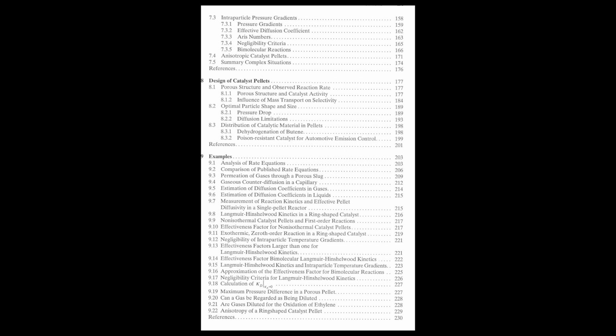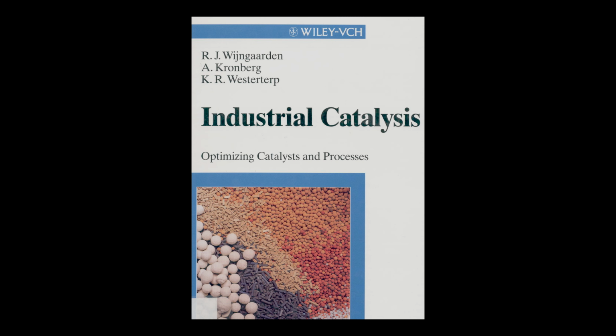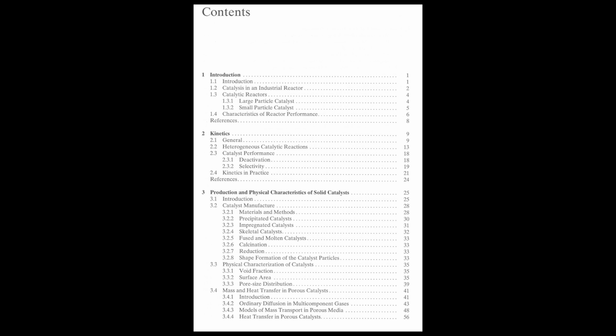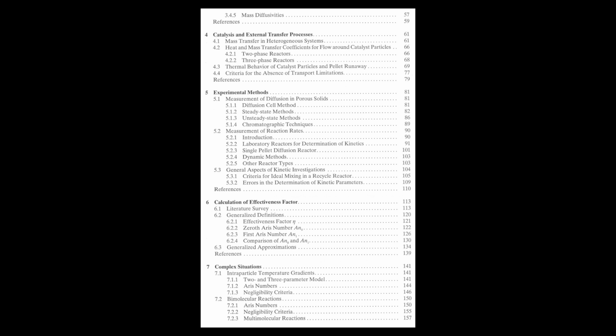This section gives us some practical guidelines and rules of thumb. It discusses criteria, with the Weisz-Prater criterion being a famous example, that can be used to estimate whether internal transport limitations, diffusion inside the pores, or external transport limitations, transfer from fluid to surface, are significantly affecting the overall observed reaction rate. How do they work? Basically, you calculate these criteria using experimental reaction rate data and the known properties of the catalyst, like particle size, diffusivity, and the reaction system, like kinetics, heat of reaction. If the calculated value falls below a certain threshold,